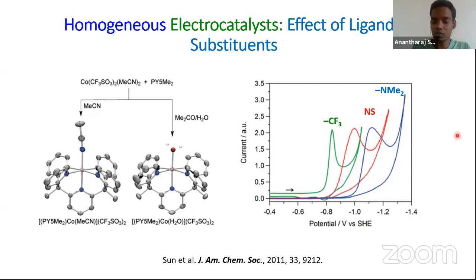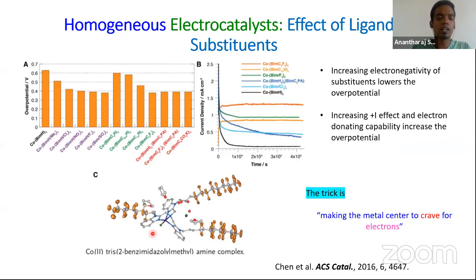So a similar study was immediately published by another group, where they created another similar complex. This is the complex, and they replaced the hydrogen in this parent complex with so many other substituents. And you can see that whenever the substituent is electronegative or a minus I group, the over potential decreases. Whenever the substituent is a plus I group and electron donating, the over potential is increasing. So the trick is you should make the metal center crave for electrons, I mean, make it electron deficient. Then you can achieve energy efficiency in homogeneous electrocatalysis for water splitting. So this is the recent trend in homogeneous electrocatalysis, and I will talk about the mechanism in the later part.